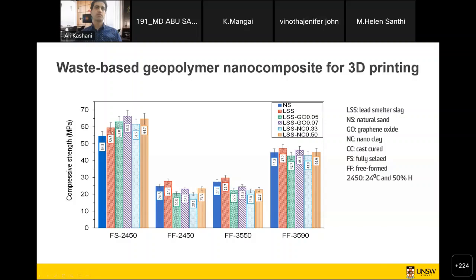You can see replacing with lead smelter slag increases the strength of the material, and adding graphene oxide and nanoclay again helps in terms of increasing compressive strength of the sample. But if you put it in the free-form condition, it's another scenario. That underhydration, that lack of water that evaporated in the early hours, really affects the performance of those nanomaterials that we put in the sample. As you can see, they are not contributing or even slightly decreasing the strength in those samples.